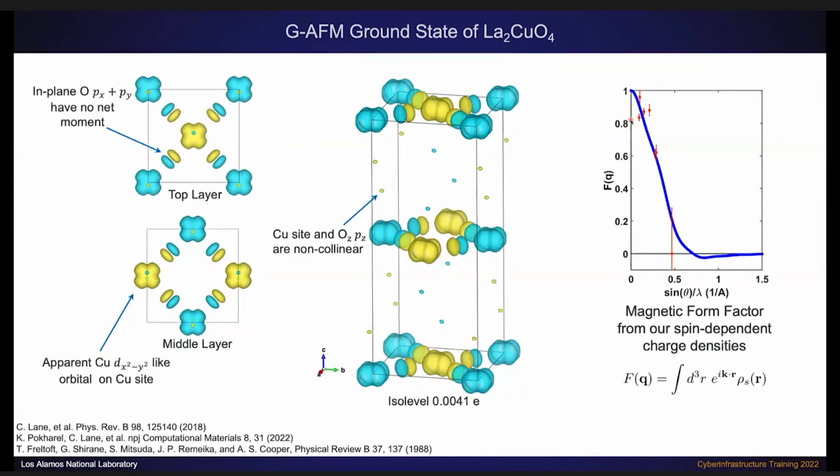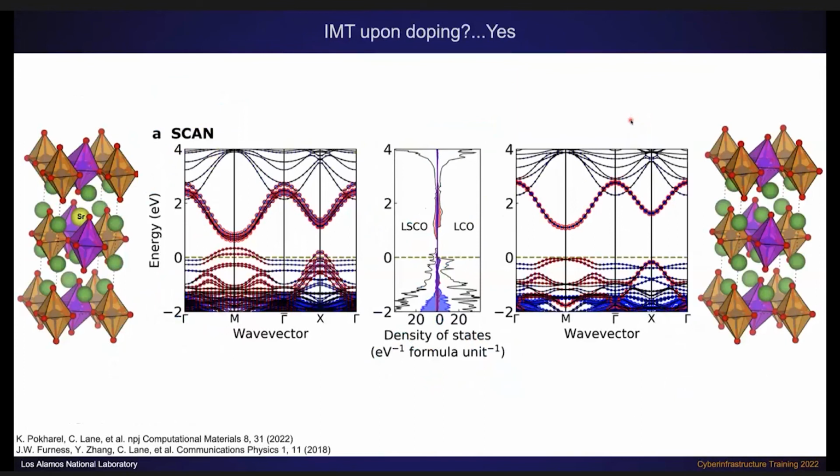Now, the main issue also was about doping. And here we also performed a doping study, and we find that as we dope the material, it does indeed become metallic. The gap shrinks a little bit due to the magnetism, but overall, we find very good agreement again with what we find characteristically with experiments. And so this is what we found for LCO, this prototypical high temperature superconductor.